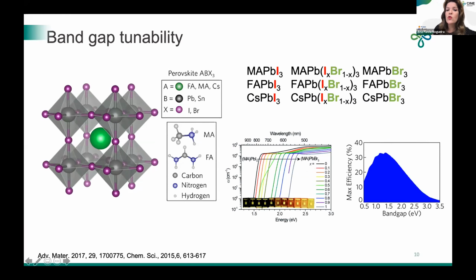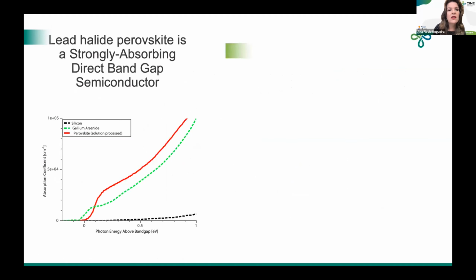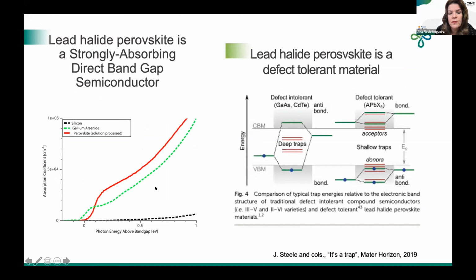There's something you can do, also playing with the A side, with the cations as well, with the monocations as well. In terms of absorption, we are doing very well because it's a direct band gap semiconductor. You can see here that absorption is much higher even than gallium arsenide if you compare with silicon. In terms of defects, these materials are very defect tolerant. Why? Because if you compare, for instance, with gallium arsenide or cadmium telluride, you can see that the traps are really in the mid gap.